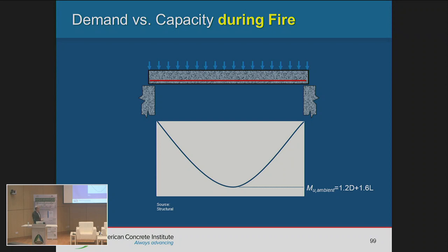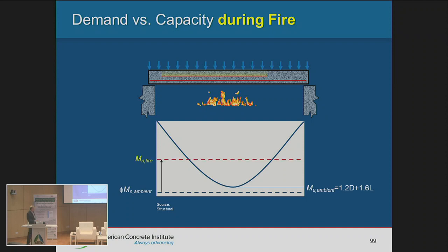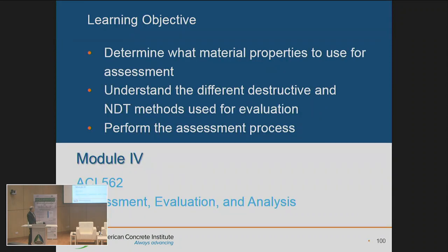When we design, your demand is this graph here, which is 1.2 dead plus 1.6 live. And your capacity is per the code, as shown here. If we have fire, the capacity decreases. It reaches here. And what we mentioned earlier, in order to use the FRP, you need to maintain a demand such that when you lose your FRP, the structure can maintain this load. It's all the same.